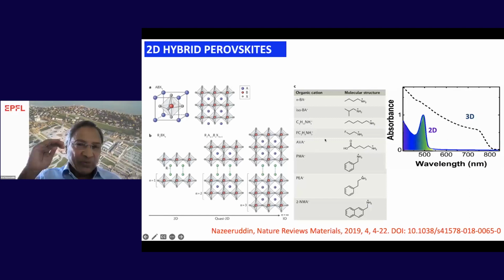If you look at the perovskite composition, ABX3, it's a three-dimensional perovskite. When we have a cation whose size is sufficiently good, that forms a three-dimensional structure. What happens if the cation size is bigger than the cavity? Then it slices this dimensionality into lower dimensionality. And this gives you the opportunity to have controlled growth of three-dimensional versus lower-dimensional perovskite compositions. Here I have taken a couple of examples of the larger cations, but we will not discuss all of them. We just take the phenylethylamine cation.